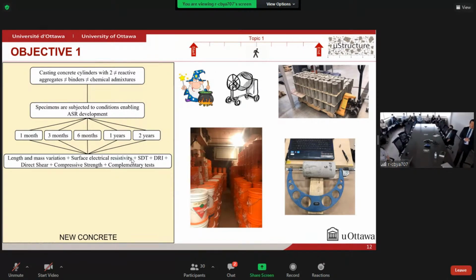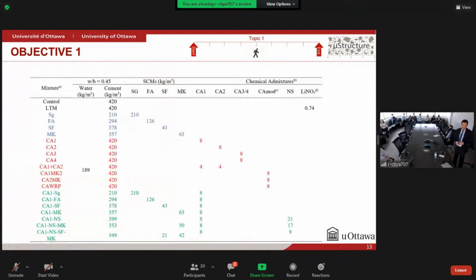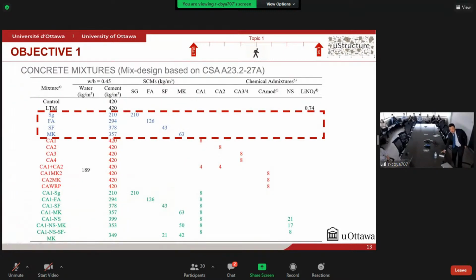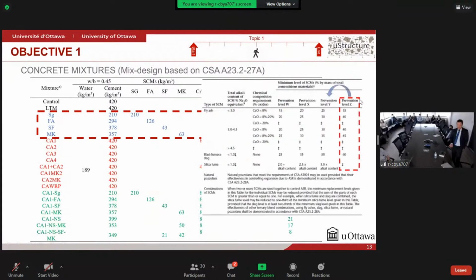So here, just a general overview of the concrete mixtures we used. Once again, we follow the mix design based on CSA A23.2-27A. We used 4 different types of SCMs: slag, fly ash, silica fume, and metakaolin, and their amount is based on the table from CSA. However, instead of using the higher amount here to avoid the development of ASR in concrete between the 2 years of evaluation, we used a little bit less to have a delay in the development of ASR. However, we are looking to have some development.